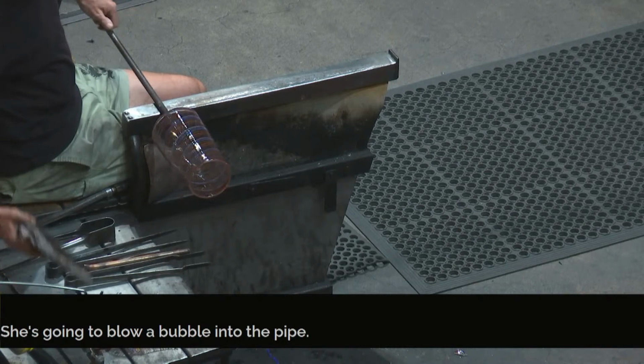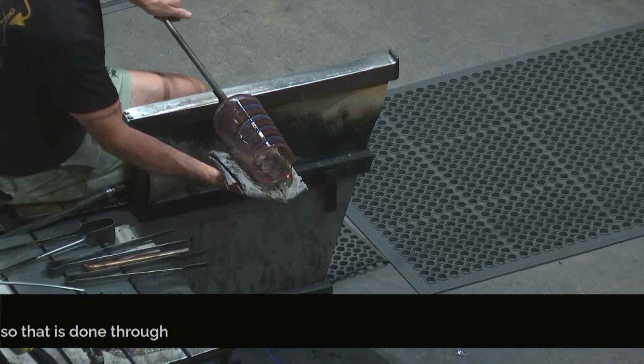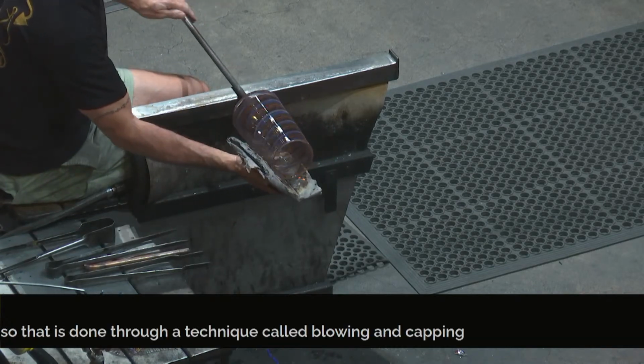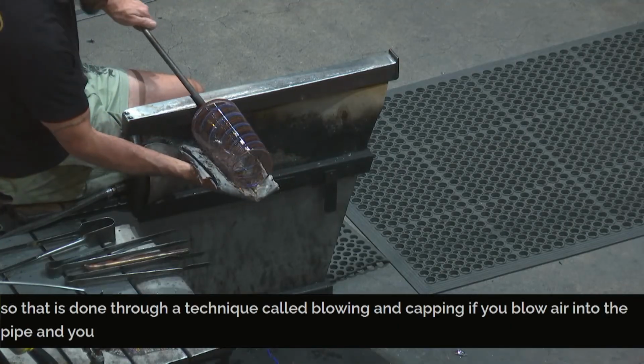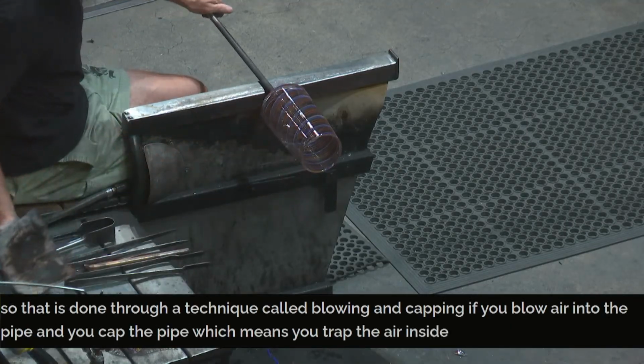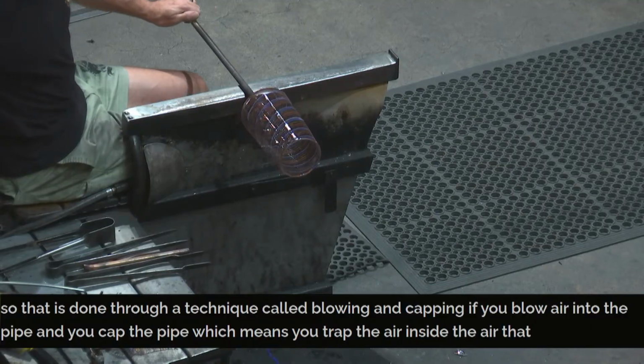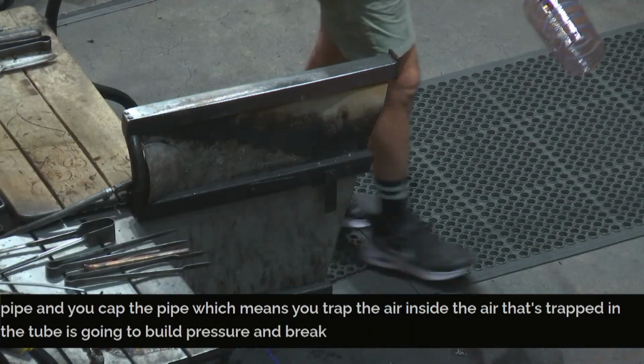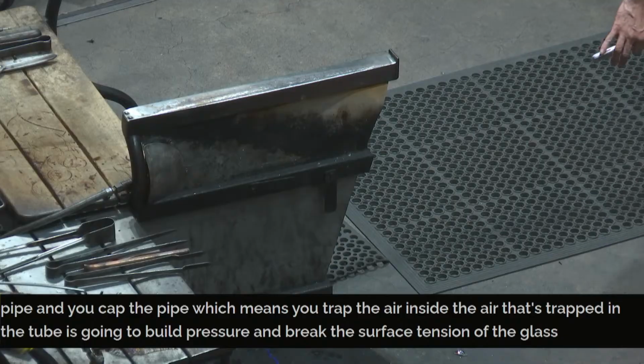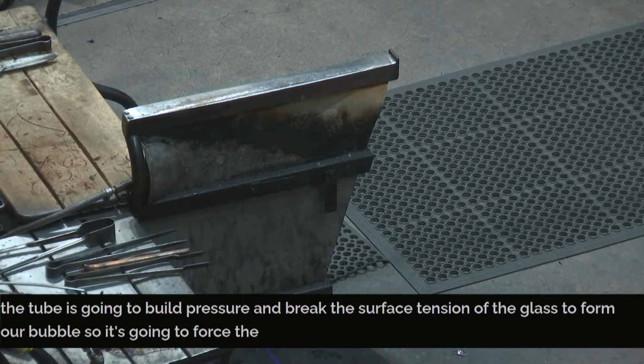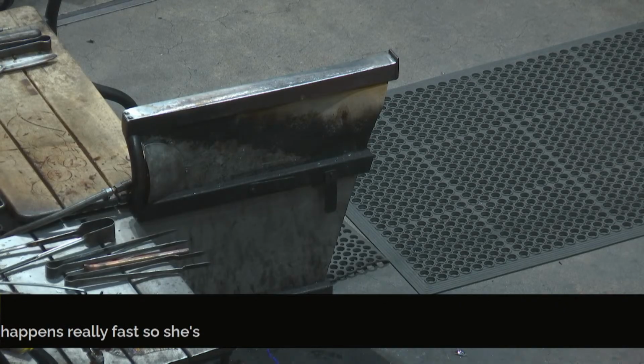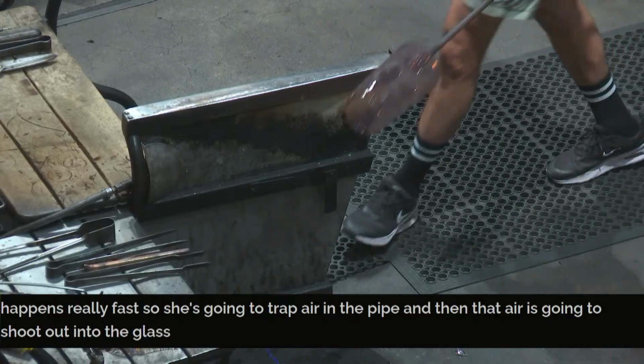So that is done through a technique called blowing and capping. If you blow air into the pipe and you cap the pipe, which means you trap the air inside, the air that's trapped in the tube is going to build pressure and break the surface tension of the glass to form our bubble. So it's going to force the air into the glass to create a bubble. It happens really fast. So she's going to trap air in the pipe, and then that air is going to shoot out into the glass to make a bubble.